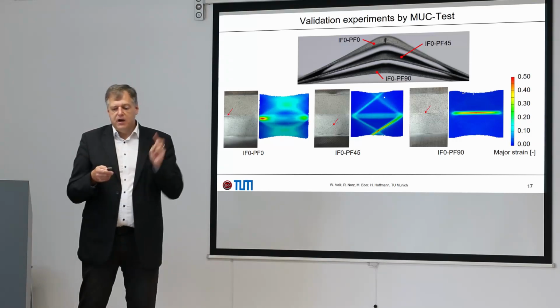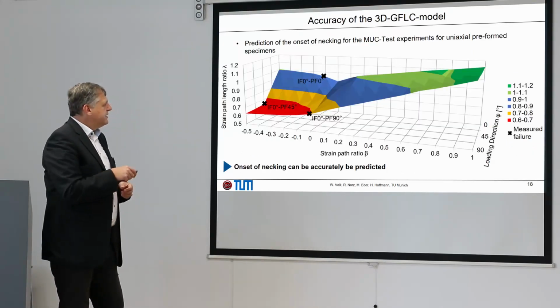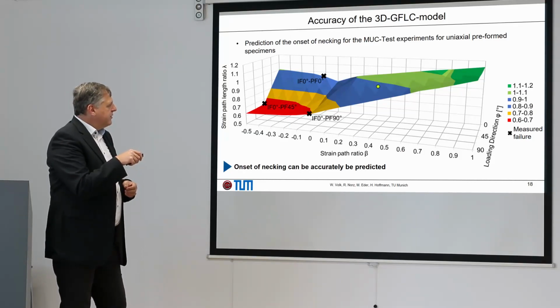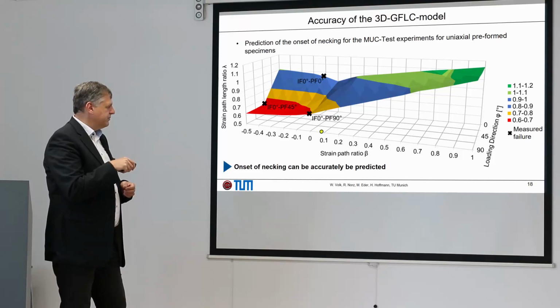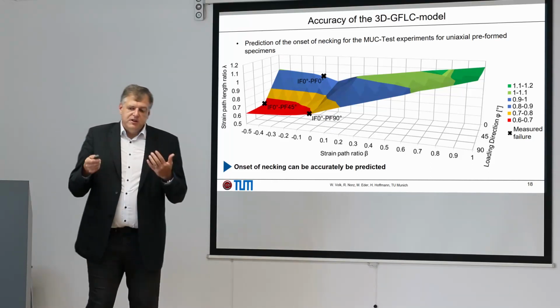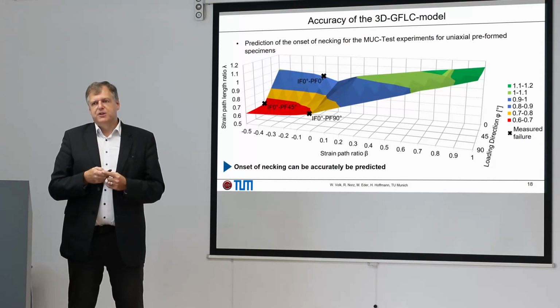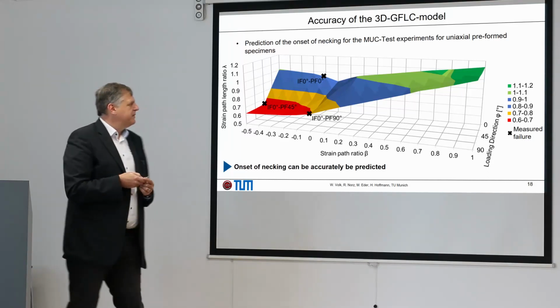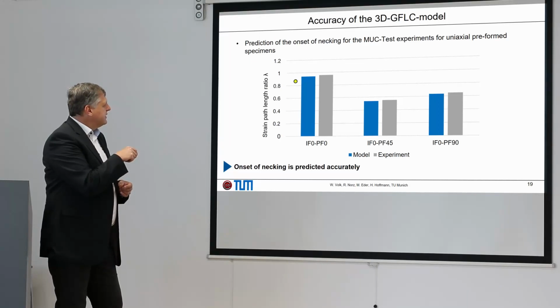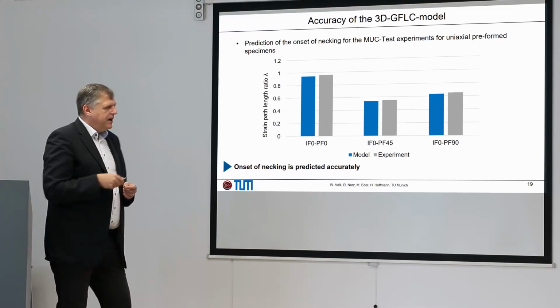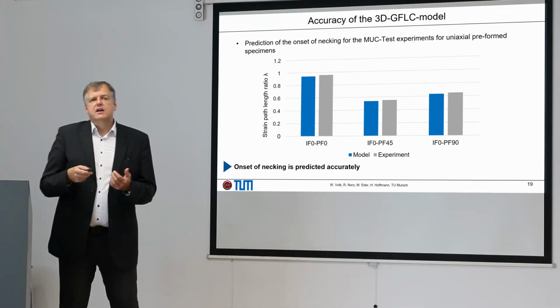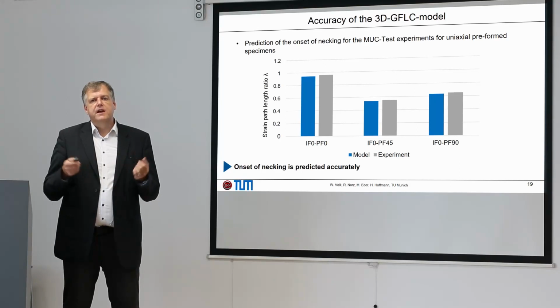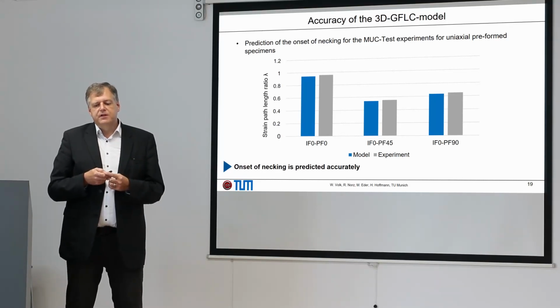And now, let's use this information to validate our generalized anisotropic GFLC model, our 3D GFLC model. Here you see the surface, which is used based on the interpolation of the experiments. And here we have these points of the 0-45, 0-0, and 0-90 combination. Also in this graph you can see seems to be an accurate prediction. And then we can have a deeper look just with a Gantt diagram, and then we see here the model and the experiments that we really have a very, very good prediction of the failure, even when we have these totally different failure modes.